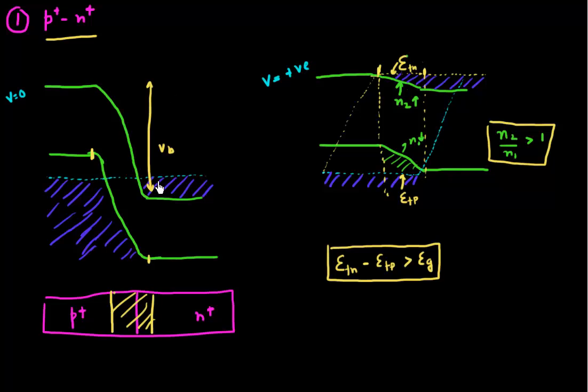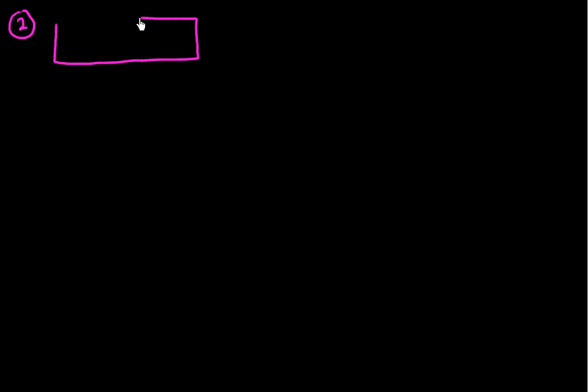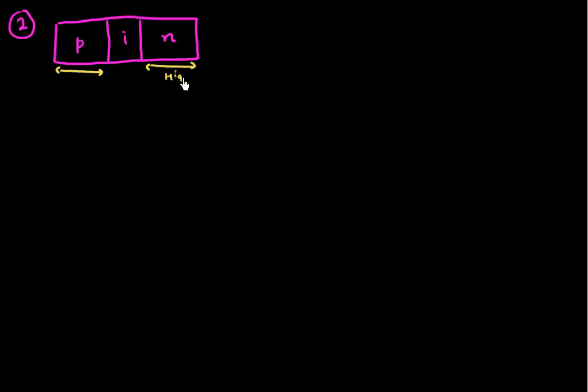This works for the case of degenerate doping. But now I challenge myself — can I do it without degenerate doping? Let me show you one case. I have a second example: a PIN diode, where none of the layers are degenerately doped. The catch here is that my P and N type layers are made up of a high band gap material, while my intrinsic region in the middle is made up of a low band gap material.